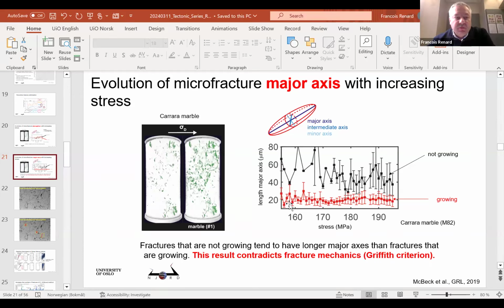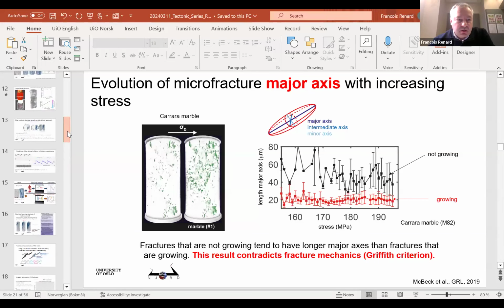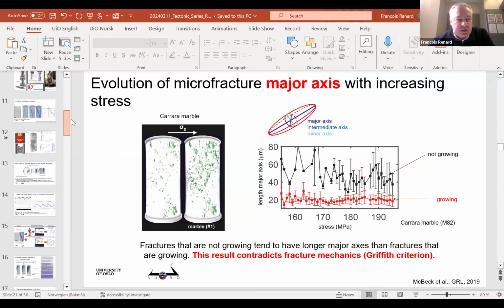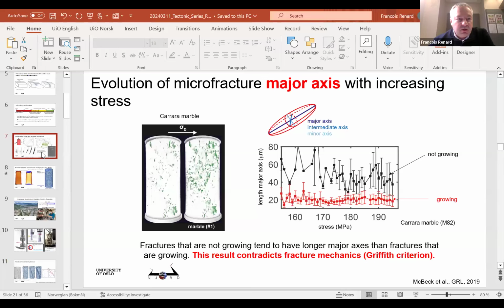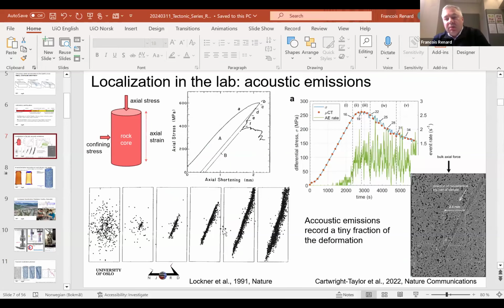And the second question, for acoustic emission, I agree it would be interesting, but there is also an important point which was raised by David Lockner, and Georg Dresen also showed that the acoustic emissions record a tiny, tiny fraction of the strain in a rock physics experiment. Meaning that with the X-rays, I can get 100% of the local strain inside the sample, more or less. But the acoustic emissions will record only a tiny fraction of it, which is on the order of 1%.